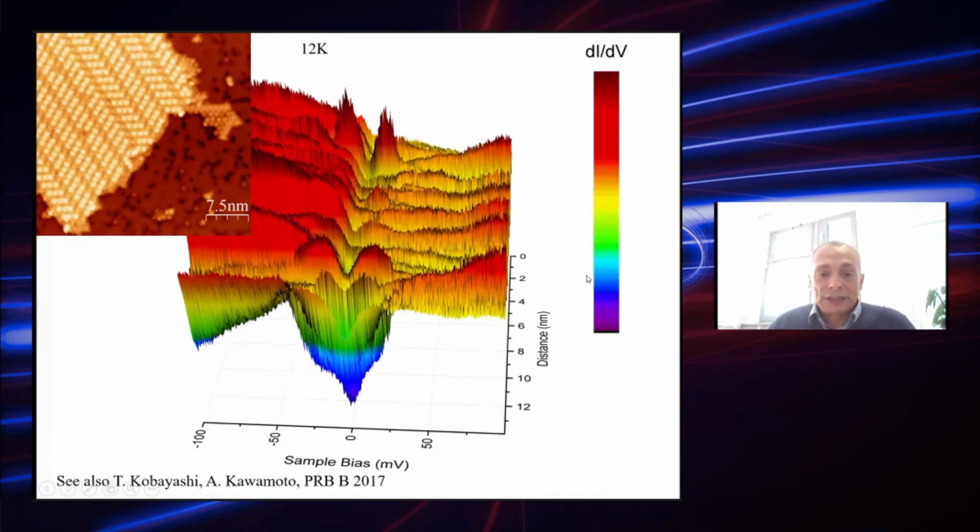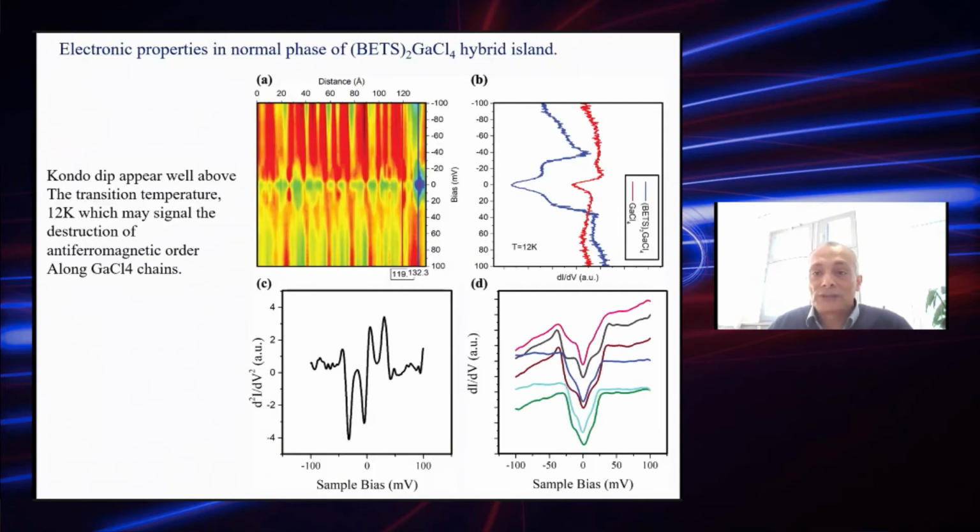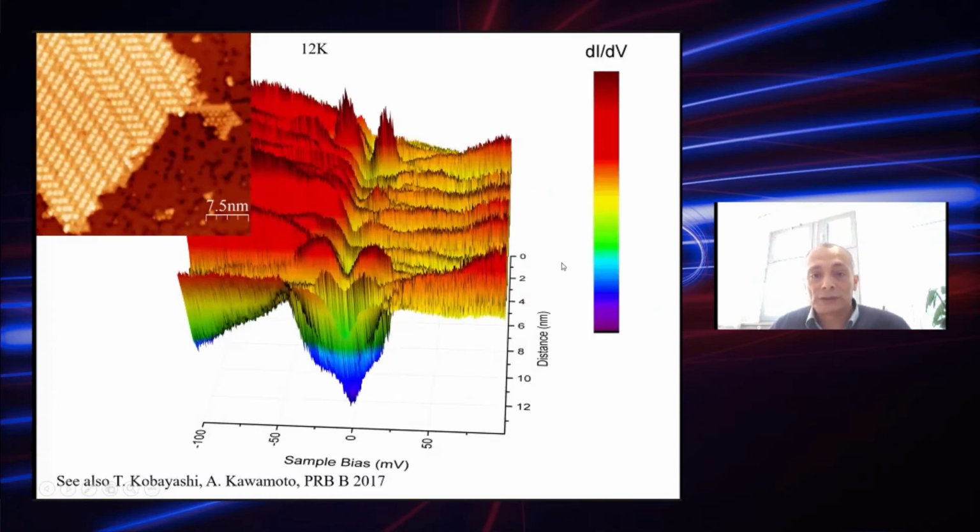And interestingly, this structure does not exist at low temperature. None of these features you can see at low temperature, right? You see just superconductivity. But above the superconducting transition, you see all the inelastic peaks. You know that these are phonons because their intensity increases with temperature as well.